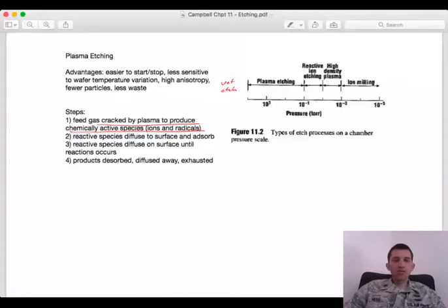And chemical processes are dependent upon cleanliness. So if you have residue on the surface, say from photoresist that was not completely removed by the developer, then you may have a thin layer of photoresist, but if your material is highly selective and doesn't aggressively remove the photoresist, then even a thin layer can protect the surface and you won't be etching areas that you had intended to etch.